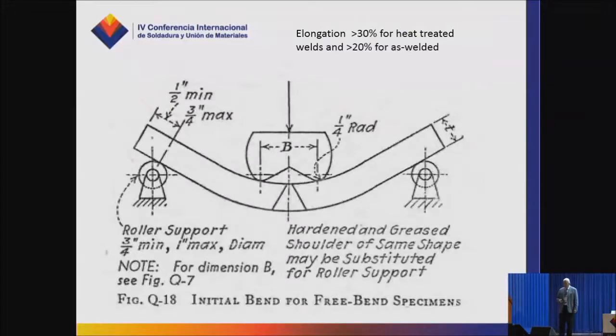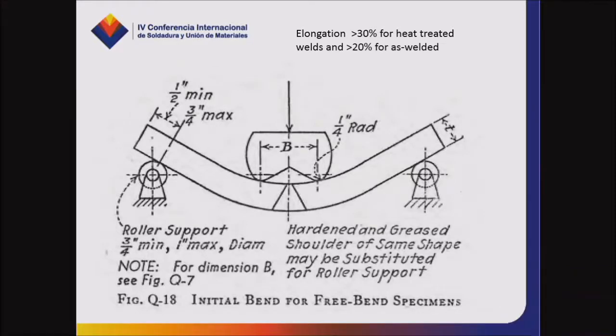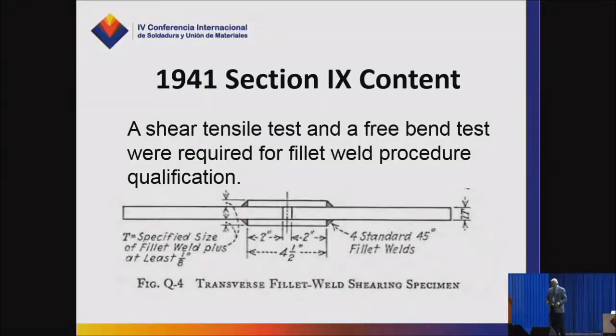A free bend test, you take a sample of the material, typically 1.5 inches wide. You put 2 scribe lines down just inside the toes of the weld. You put it in a fixture and you bend it until the sides are parallel, and then you measure the elongation between those 2 scribe lines. And the code said that the elongation had to be 30% for welds that were heat treated, 20% for welds that were not heat treated.